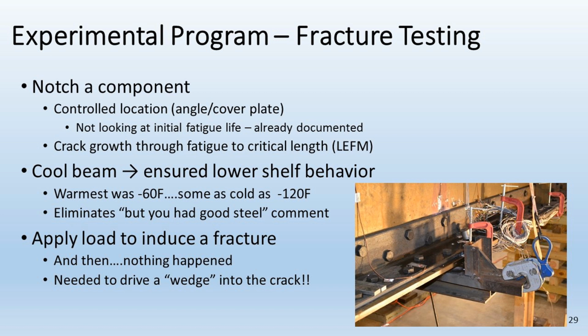Well, its ability to tolerate that kind of dynamic loading, its toughness, drops with temperature. In other words, I am better at tolerating a crack at a warm temperature and higher toughness than at a cold temperature and lower toughness. And so the tests are done at cold service temperatures, right? If you have a bridge in North Dakota, as we saw this year, we can get down to some very cold temperatures, and a crack that maybe is stable in August is no longer stable in January.